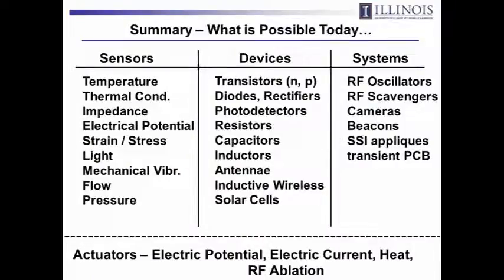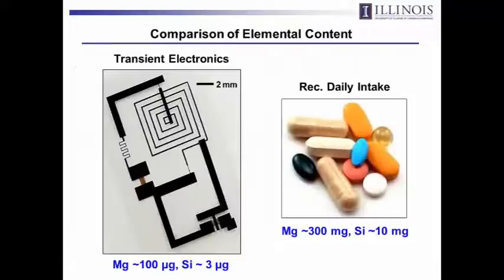And so that's kind of where we are. Let me try to give you a sense of what is possible. We've demonstrated, and I just showed you a fraction of these, components: sensors, devices, and then integrated systems. We do a lot of different kinds of measurement: temperature, thermal conduction, impedance for skin hydration, for example. We measure electrical potential, strain, stress, light. I showed you the camera, mechanical vibrations of that zinc oxide harvester. We measure flow and pressure. We've done transistors, diodes, rectifiers, photodetectors, resistors, capacitors, inductors, antenna, wireless coils, solar cells, and then in some cases we've taken these components and put them into very simple systems, but at least things that have overall function. So I think it's still very much early days in the development of this technology, but we can already do a fair number of things and hope to expand on that over time.